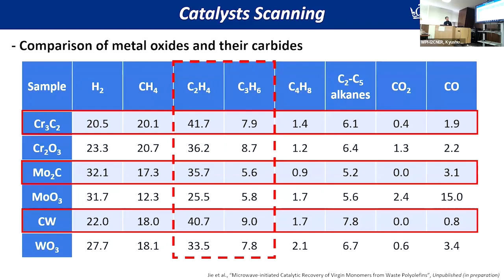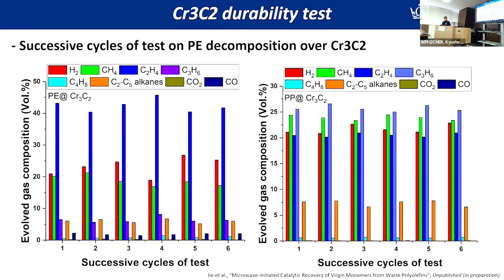But we are hoping we can achieve better selectivity and yields in the very near future. At least we found these carbide materials perform with good catalytic activity and also respond to the microwave well. The good thing is we have run successive cycles of tests and we find less coke formation, and that is a good sign because coke formation is always a problem in such chemical reactions.